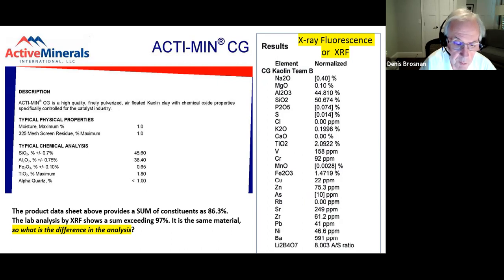So look at the typical chemical analysis on this data sheet. Silica, percent, average 45.6. Well, there's plus or minus there, a little variation that they allow themselves to take. It's a natural material, so there's going to be some variation. Alumina content, weight percent. These are in weight percent. Typical chemical analysis is 38.4%, plus or minus a little bit. A little bit of iron oxide, and it's very low, about 0.85%, plus or minus a bit.